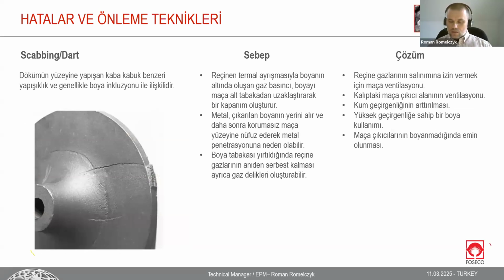Another one is coating scabbing, and again, it is connected in many cases with the mold and core: gases, permeability, the surface quality of the mold or core, and the release agents used for it. Maybe, for example, there is too much, and the coating does not adhere enough. So the adhesion between the coating and the core after drying is not enough. It means during or after casting, the liquid metal will not be enough to keep the coating on the mold. Gases will remove, like explode, the coating from the surface, and the coating will float on the liquid metal and create that kind of defect.